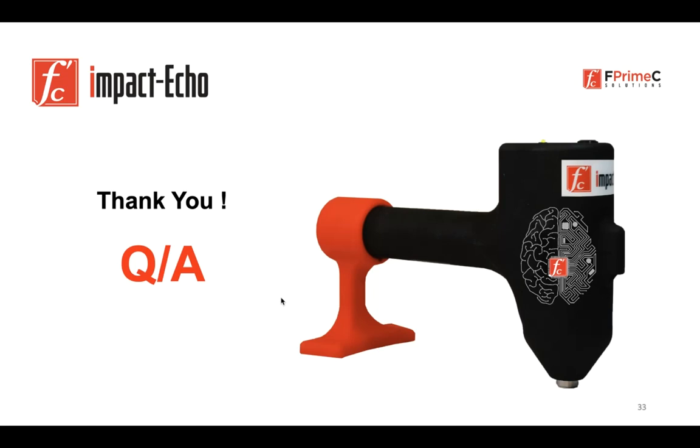Impact echo results can be affected by the steel reinforcement. Otherwise, at other locations of the column or the slab, where there is no congested reinforcement, of course you can use the impact echo. Based on that literature review, I don't see the reinforcement affecting the test results by more than 5%.